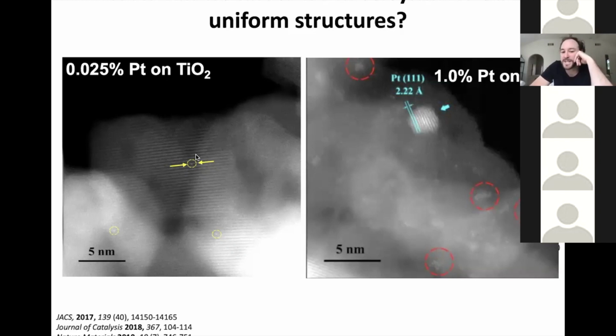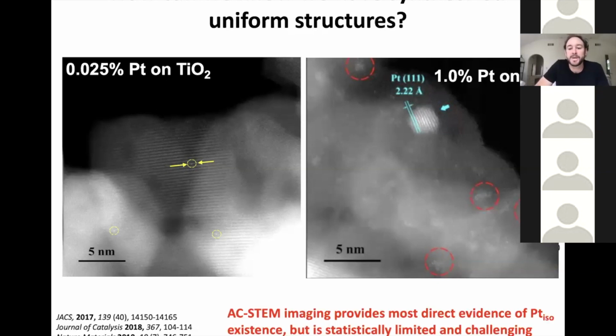If you compare the materials we made using this electrostatic adsorption at very low loadings to those made at 1% or so, you see all sorts of different species here that don't exist here. So just qualitatively looking at the microscopy, it seems this sample on the left has more uniform and mostly isolated structures as compared to the sample on the right. So in my perspective, microscopy provides the best direct evidence that you have single atoms, but it's statistically limited and can be challenging to interpret.